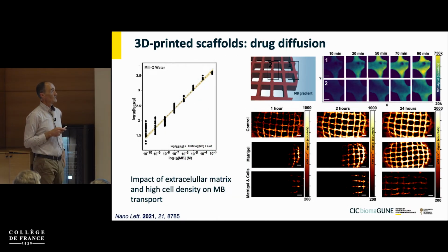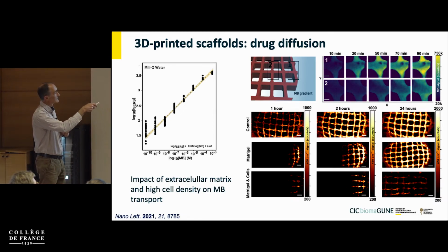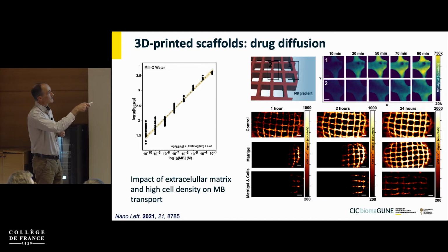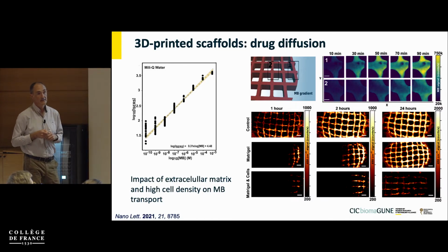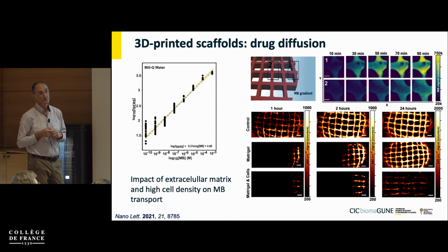And then these are some of the initial studies, basically to see by Raman the diffusion of the drug through the system. So this is the sketch where I show you this would be the reservoir where we inject the methylene blue. This number 1 is this area that we watch here, very close to the reservoir. So at different times you see how the intensity is increasing when you try to detect the methylene blue, only exactly at the places where you see the scaffold.